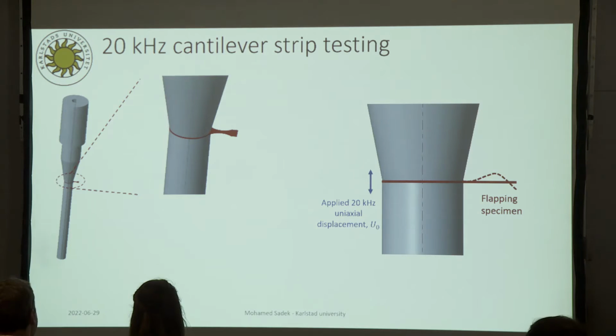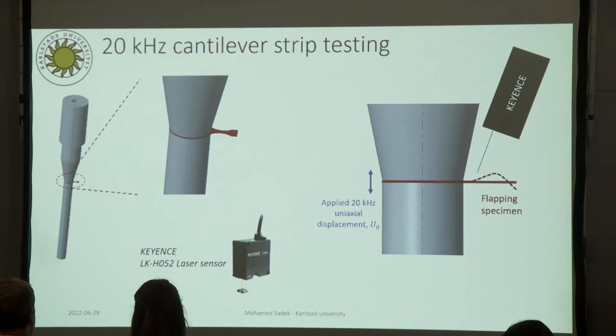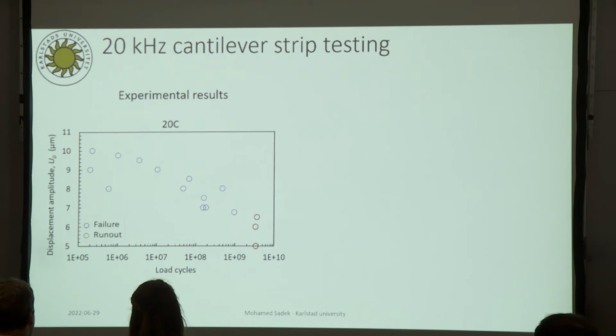This is a 3D CAD model of the setup. Over there you can see a close-up of the specimen sticking out like a cantilever specimen. We have the applied displacement in the horn right here, called U0 throughout this presentation, which is what we control during the experiment. And then we will have a flapping specimen. We have also measured the displacement along the specimen with a laser sensor to try to confirm the calculations and the predictions.